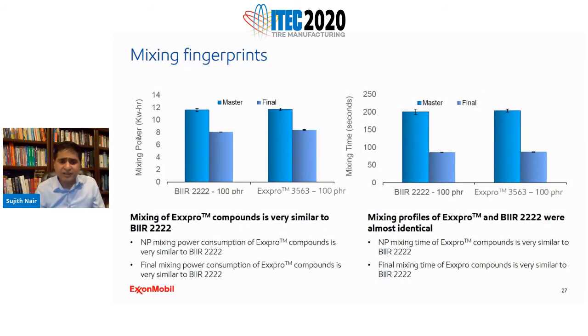So looking at the mixing fingerprints, again, Exxpro processed the same way as that of bromobutyl. Two things that we look for, because we are actually dumping based on the temperature, are the mixing power and the mixing time. We look at the mixing power because we want to see whether the material took similar, equal, or lesser power than that of bromobutyl. In this case, again, the mixing power was pretty much the same. So we can say that the mixing is very similar to bromobutyl. The mixing time was also very similar. We are again dumping based on temperature, and this shows that Exxpro has almost the same mixing characteristics as that of bromobutyl.